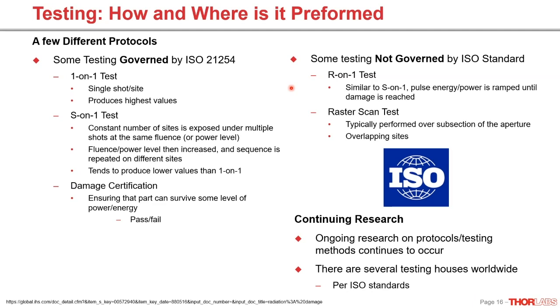And then I believe the ISO standard also covers damage certification, which is just, will this part take this amount of power and or energy? And that's a pass-fail test. So that's relatively simple. There are a number of tests described in the literature that I don't believe are governed by the ISO standard. So one of those is the R-on-1 test. This is similar to the S-on-1 test, but this is focused on the same site, so the power is going to be ramped until damage is reached, rather than hitting one site, seeing no damage, and moving on to another site.